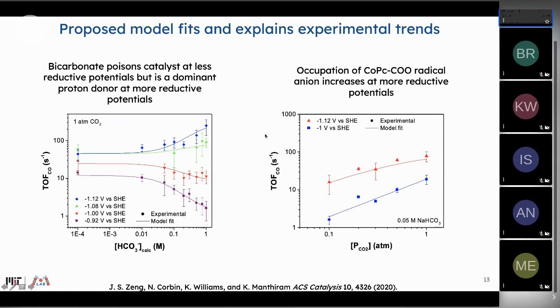We also see that many of these non-unity orders that we observed for CO2 order, this is related to occupation of the CoPc sites by a CO2 radical. And so as we go to higher CO2 partial pressures, we have greater occupation of the active sites. That in turn suppresses the apparent order in CO2, especially at higher overpotentials.